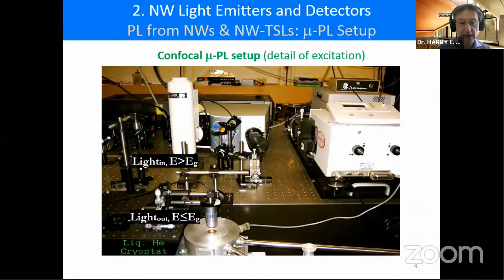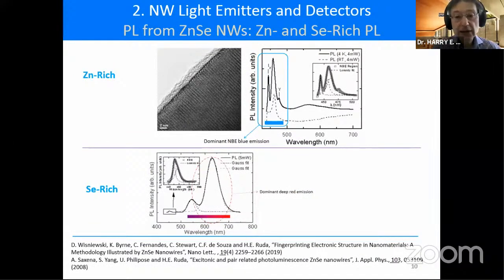And this is just another detail of the cryostat, which we pump down to 1.6 Kelvin. All right, so as a change of pace from the indium arsenide and indium antimonide I've been talking about, I thought I'd talk a little bit about zinc selenide. It's an interesting optoelectronic material, a direct bandgap material, and interestingly, you can grow it very pure. It's single crystal, as you can see from the inset at top. But by changing the stoichiometry of the environment, that is the ratio of the zinc to selenium partial pressure in the vapor, we can change the outcome of the luminescence, the photoluminescence.